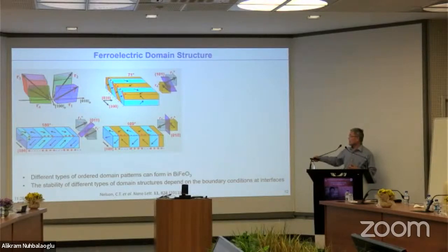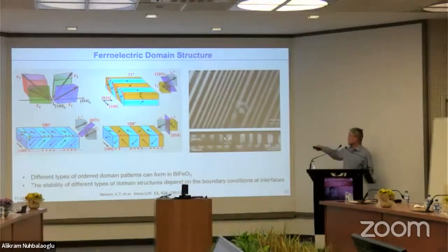So overall, with this kind of material, you have three different kinds of domain wall types. And this domain wall motion dynamics will determine the property and functionality of the ferroelectric material. This is just the TEM image showing how the domain structure looks in the TEM. In the plan view TEM study, an electron beam is delivered to the surface, and then all these domain walls will appear as stripes, running parallel along the beam direction.